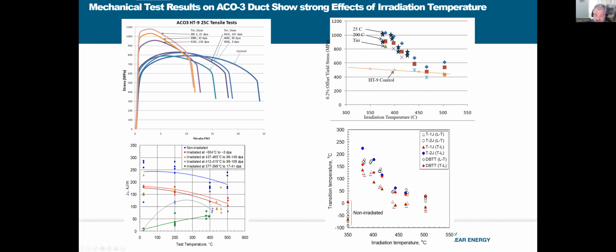These green dots here are samples irradiated at 377 to 398 degrees C. This is work that T.S. Byun did many years ago. And he also measured the ductile to brittle transition temperature, and you can see that the hardening, of course, leads to an increase in the ductile to brittle transition temperature. And the sodium handling temperature for a sodium fast reactor is around 200 degrees C. So you're getting to the point where you're close to becoming brittle at the sodium handling temperatures, which is not what you want.